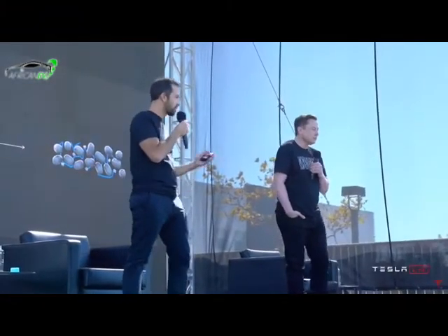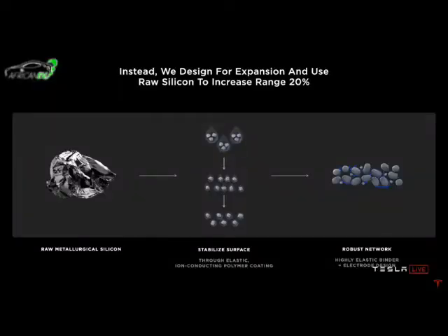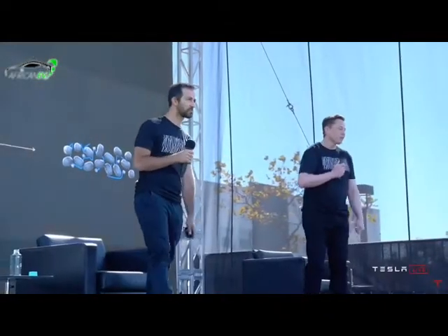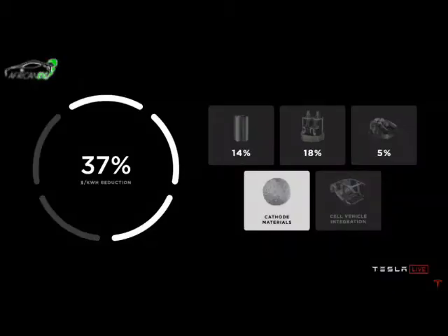And how does it work? Start with raw metallurgical silicon, stabilize the surface with an elastic ion-conducting polymer coating that is applied through a very scalable approach. No chemical vapor deposition, no highly engineered, high-capex solutions. Then it's integrated into the electrode through a robust network formed out of a highly elastic binder. And in the end, by leveraging this silicon to its potential, we can increase the range of our vehicles by an additional 20%, just from this improvement. Yeah, it gets cheaper and longer range. And when we take that anode cost reduction, we're looking at another 5% dollar per kilowatt hour reduction at the battery pack level. And there's more.